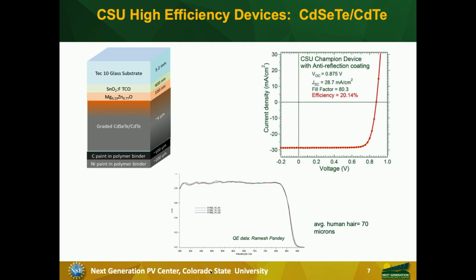And then we start with cadmium selenium telluride and then cadmium telluride, and we blend the stuff together. So there is a selenium blending that goes on from the top to bottom, and the total thickness is about 4 micrometers. An average human hair is 70 microns thick. So you're talking about very, very small amount of material that is required to make the solar light into electricity. That's one of the big advantages of this technology. And then we put a tellurium layer at the back and then carbon and nickel paint, and that completes the device. The best we have done is 20.14%.